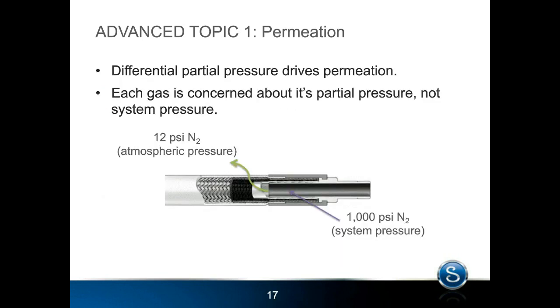So when we talk about permeation, permeation is interesting because gases permeate in the direction where their partial pressure is lower. So it's a little bit non-intuitive. But if we look at this example here where we have air on the outside, and air consists of about 12 psi nitrogen and about 3 psi oxygen, give or take. And on the inside of this particular hose, there's 1,000 psi nitrogen. So the pressure differential in nitrogen is 988 psi on the inside. So nitrogen will permeate out of the hose at a rate equivalent to 988 psi differential. That tends to make sense.